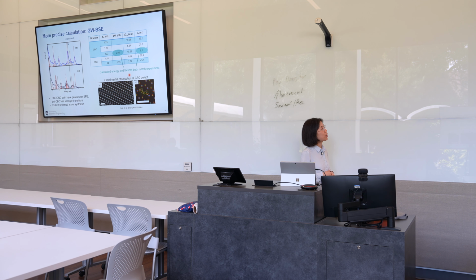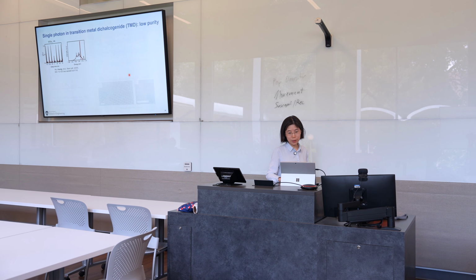All right, so this is the story about single photon emitters in boron nitride. Now, let me switch gears a little bit and talk about another host material for single photon emitters, which is transition metal dichalcogenide, or TMD. For single photon emitters in TMD, a conventional issue is the low single photon purity. This is a normal single photon emitter in tungsten diselenide, a type of TMD, that you can expect. This G2 here is about 0.4. This translates into a single photon purity of about 60%. So apparently it's not enough for a number of applications.